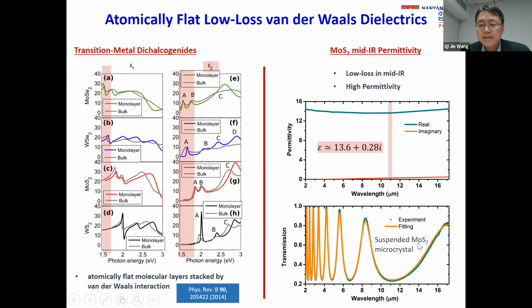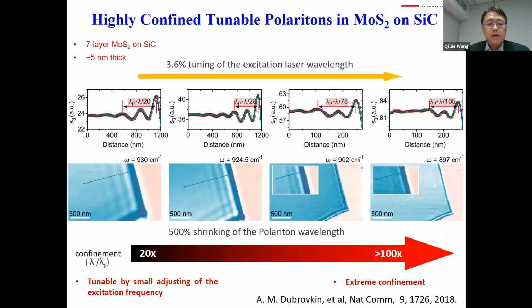So this gives us a confidence to further investigate the loss property of such material. And then we use a suspended MOS2 material, and through the transmission measurement, we characterize the permittivity of such 2D material. And we found that it has a relatively constant large real part of the permittivity, 14, and relatively low loss in this whole mid-infrared region. Okay, and therefore we make such device and use the SNOM system to measure the near field imaging directly. And the figure in the middle shows very nice interference fringes.